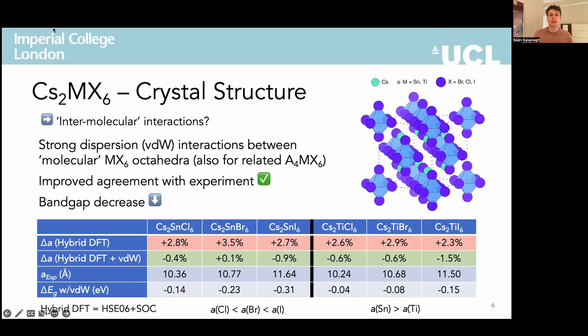Moreover, this lattice contraction has a significant effect on the electronic structure, tending to reduce the bandgap energies. These results demonstrate the necessity to account for these molecular-type interactions in theoretical models of this and related zero-dimensional compounds.